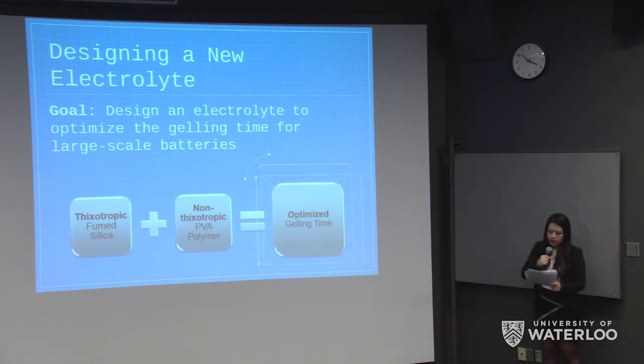So our electrolyte design comprises a thixotropic additive, fumed silica, and a non-thixotropic additive, PVA polymer, which is polyvinyl alcohol. And by manipulating the ratio between these two additives, we wanted to optimize the gelling time. We chose the PVA polymer for a lot of reasons, but some of the most important ones are the fact that it's hydrophilic, so it likes to grab onto the water that's in solution, and it also keeps the shape of our gel electrolyte intact. And also it has high tensile strength and flexibility.